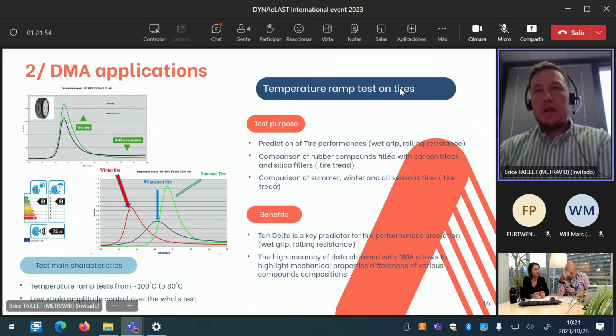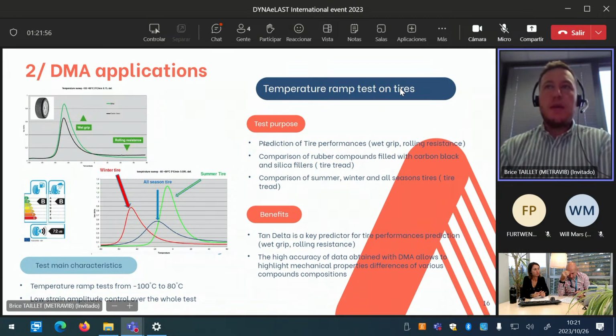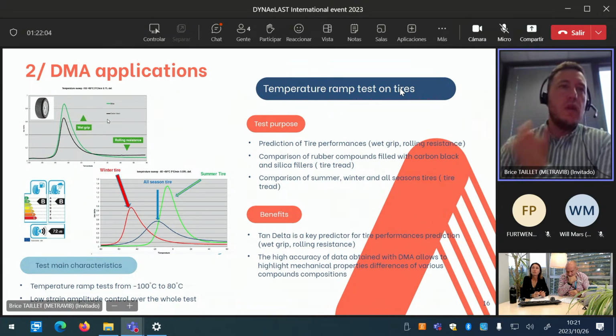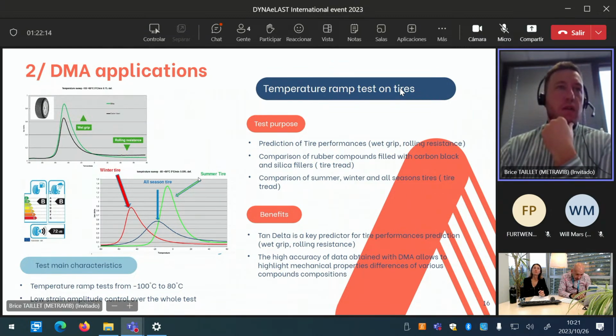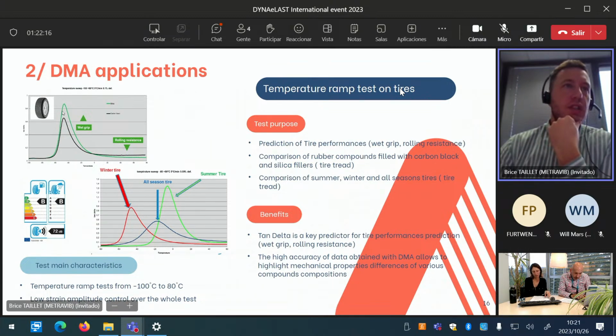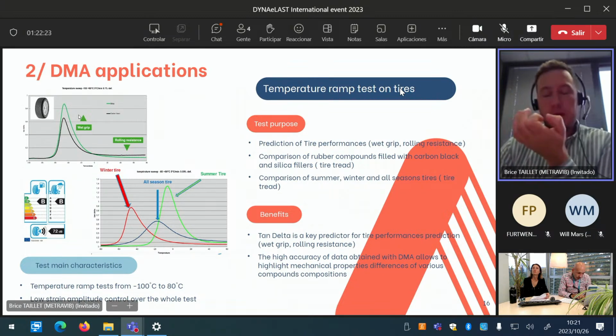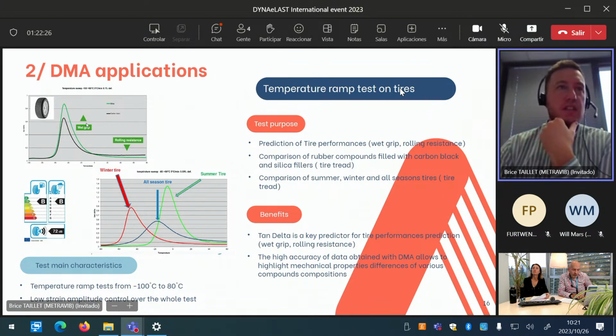One other test, temperature ramp, but on tires. And I would like to show you these curves. Actually, we are working so closely with Michelin, Continental, Bridgestone, Pirelli, and DMA in such cases are used mainly for this kind of thing, to get the tangent delta as a function of temperature, because actually tangent delta is a key predictor for tire performance prediction. That is to say, the wet grip or the rolling resistance.